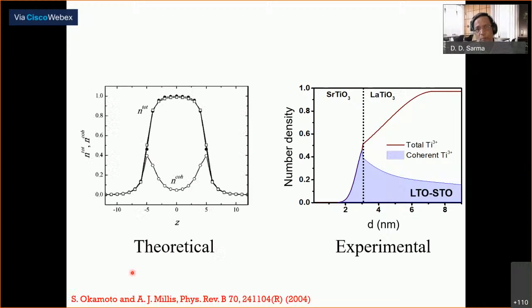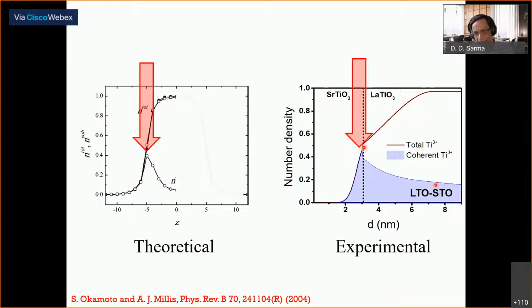And the same thing can be compared with the calculation. The calculation had symmetrized the sample, so we can ignore that part. And you see that the total electron density behaves this way, which is to be compared with this line. And the coherent intensity is this one, that is to be compared with this one, except for, as you can see, that here the distribution is over a little longer range of distances than is predicted by this.